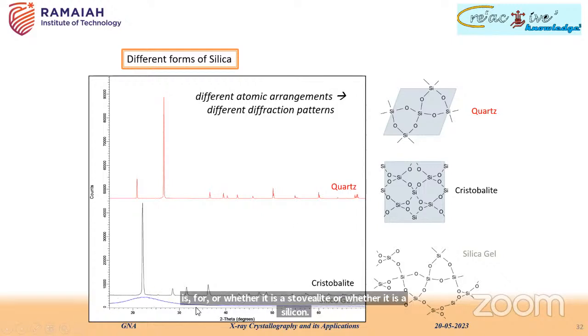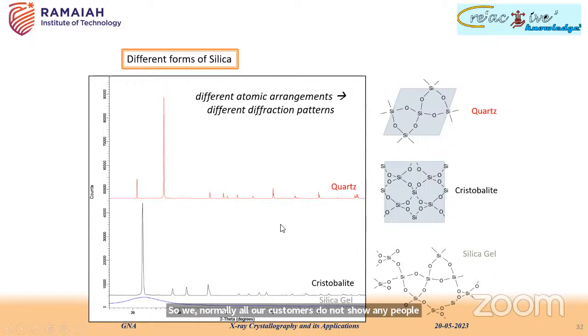See, silica exists in 3 forms: quartz, cristobalite, and silica gel. Silica gel is amorphous in nature, and cristobalite and quartz are different. One is tetragonal, another is hexagonal. The cristobalite has a different pattern compared to the quartz. Here we can notice that the powder diffractometer identifies the exact phase of the material. So we can quickly identify whether the material is quartz, cristobalite, or silica gel. Amorphous materials do not show any peak at all, because they do not have a regular arrangement, whereas other crystalline materials with different symmetry give a particular peak pattern.